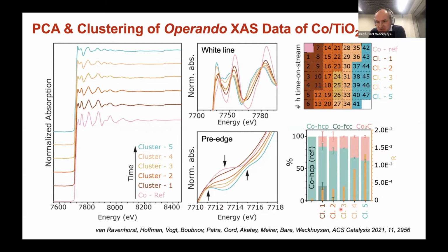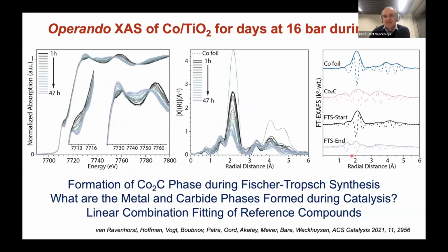Well, if you put these clusters and you look into what their contributions are of the different important phases, here you see hexagonal close packing for cobalt, FCC packing for cobalt, and a carbide. And you gradually see this formation of the carbide and decrease, as I already showed with X-ray diffraction.